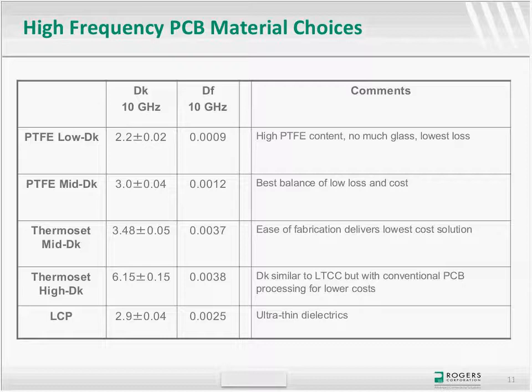Mechanically speaking, these materials tend to have mechanical properties very similar to traditional FR4 epoxy glass kind of circuit boards. They don't have the PTFE, as we said. It's a different kind of resin system, low loss, not as low as PTFE. And they also use ceramic filler, and typically these materials are coated on a woven glass matrix to give the individual layers that get stacked up to give the various different thicknesses that are needed.